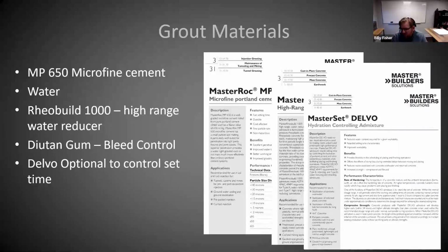So the Diutan Gum was what we used to control the bleed. In many applications under pressure, you're trying to keep the water from separating from the mix because you're pumping into a mass. This is especially important here because we weren't sure what type of voids we would encounter, if they were larger voids. We needed the bleed to be stable for the grout, so it would uniformly suspend until the grout was able to set, and everything would be uniformly distributed into the void space.